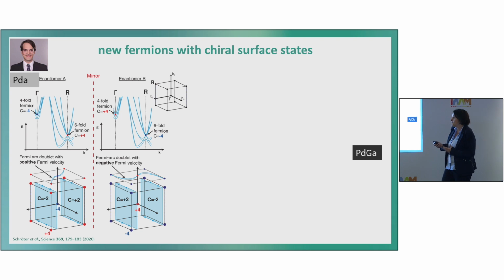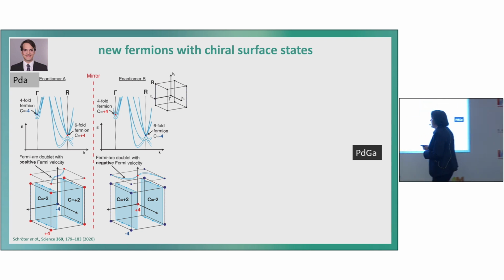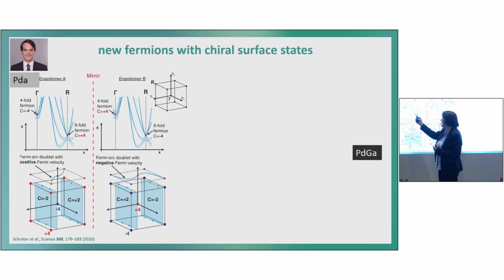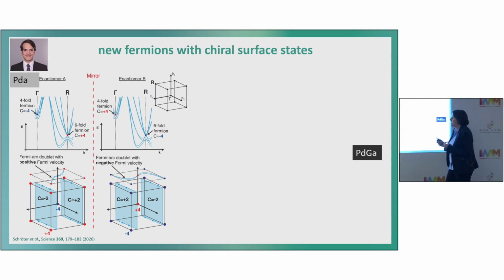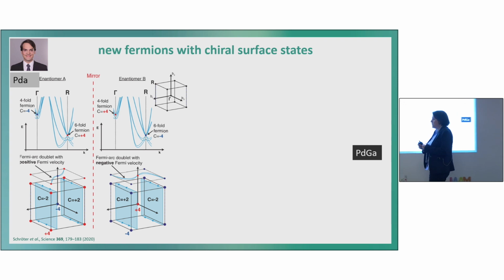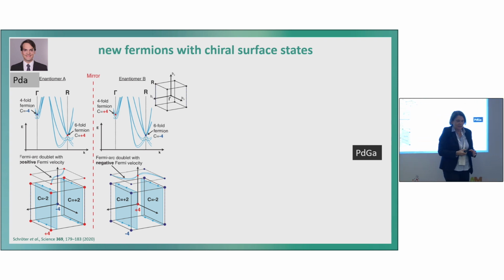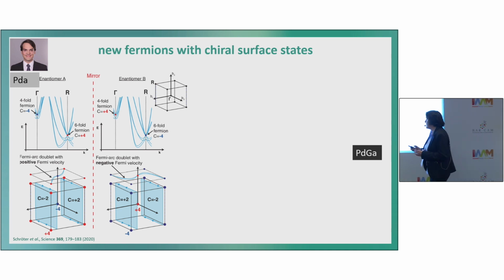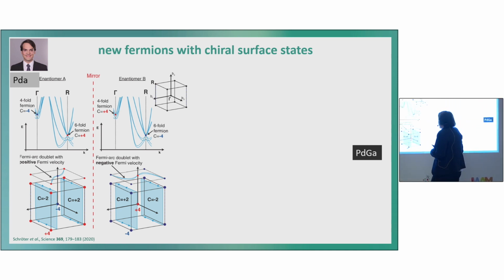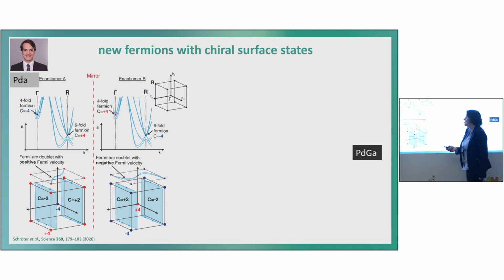The other thing, maybe more for the experts in topology, was also very interesting because we have this higher-fold degeneracy. On one point, it's a 6-fold fermion. On the other point, it's a 4-fold fermion. And they had a higher Chern number. So it was not only a donut that we discovered, but a super bretzel. So in this sense, we had this higher Chern number, and it was interesting to prove that we have it in this material. And they have different signs at these different points.